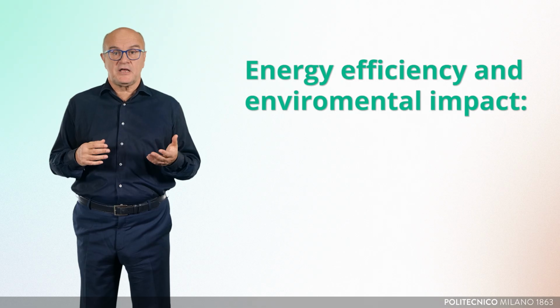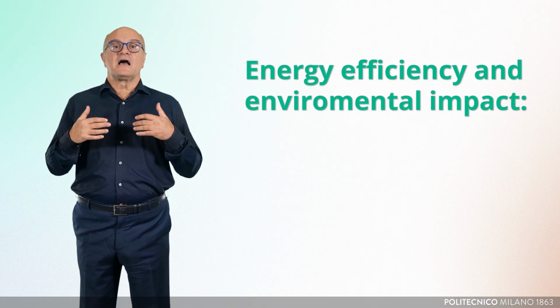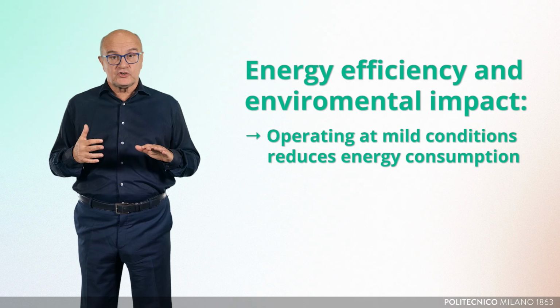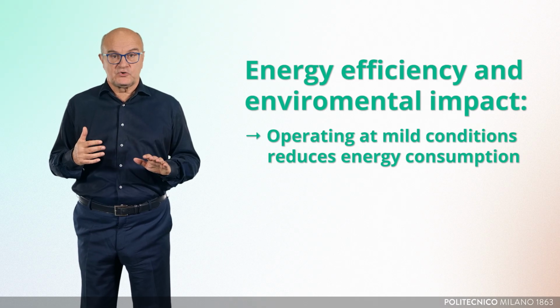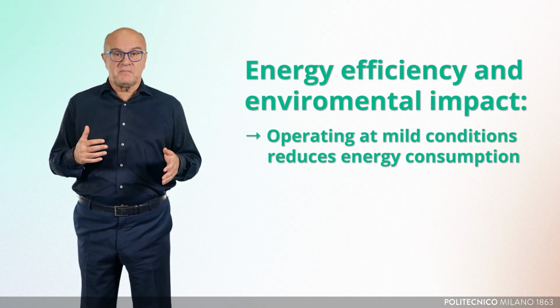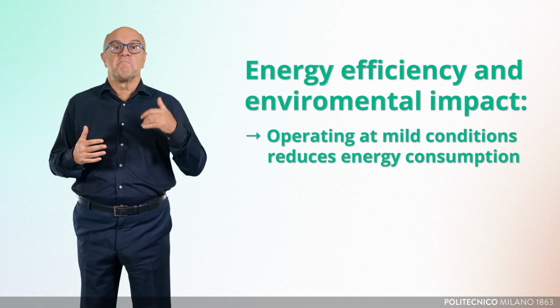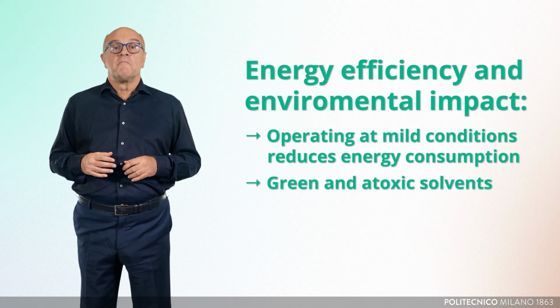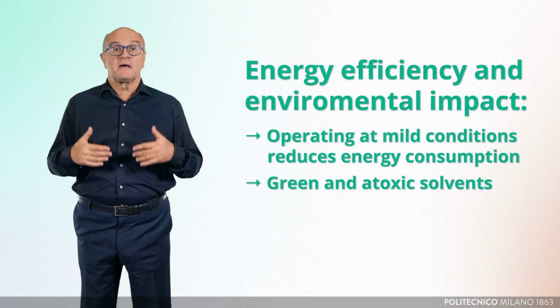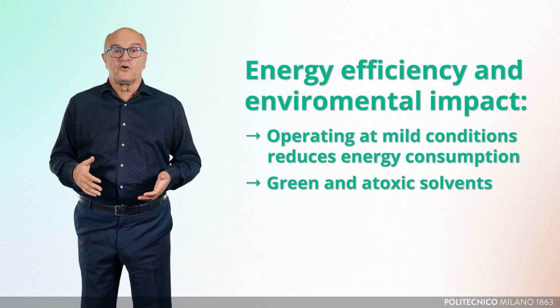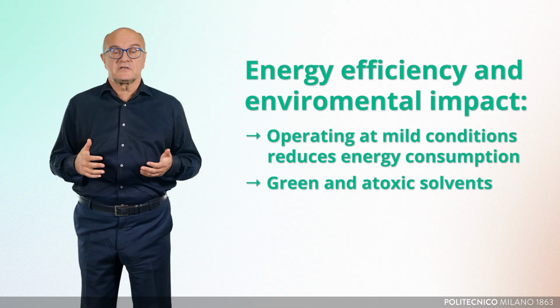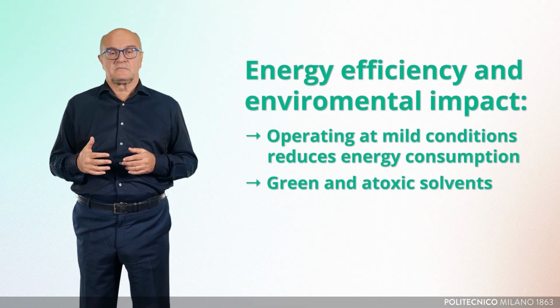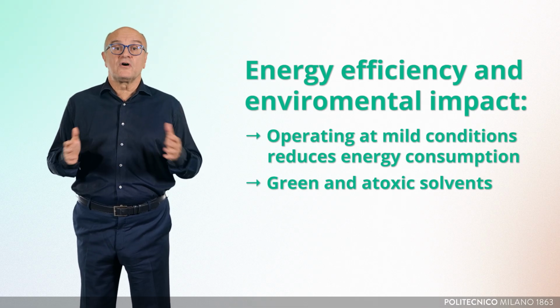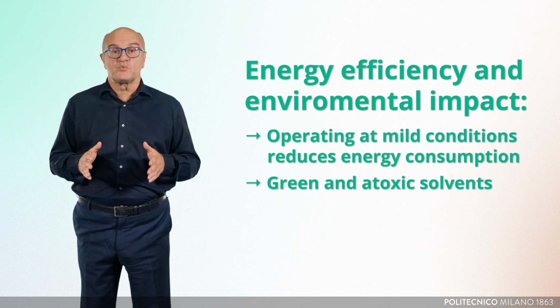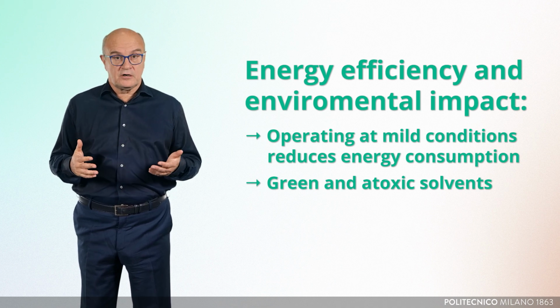Third point, energy efficiency and environmental impact. Catalysis allows to operate at mild conditions and reduces energy consumption compared to thermal recycling methods like pyrolysis, which require much higher temperatures. Moreover, green and atoxic solvents can be used. They can be fully recovered by distillation at the end of the process and used again and again several times. Solvolysis avoids toxic emissions and reduces waste, contributing to a true circular economy.